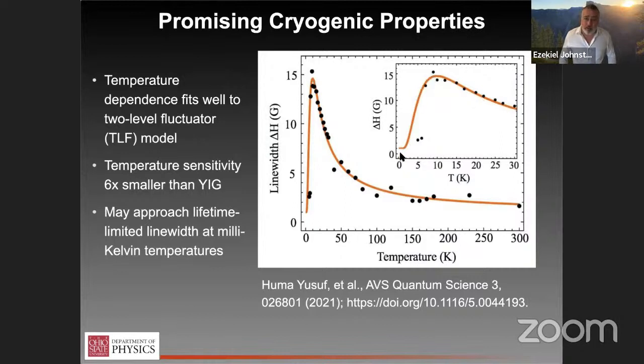So this downturn at low temperatures is when some new physics takes over, however. And here we have to move beyond that quasi-equilibrium view and really look at the dynamics, which is, I think, kind of fun. So if you start thinking about the spin lifetime of those paramagnetic spins, which should be continuously increasing as the temperature drops, and the magnon scattering time, that mean magnon scattering time. So how long after the first magnon hits it does the second magnon hit the same paramagnetic spin?